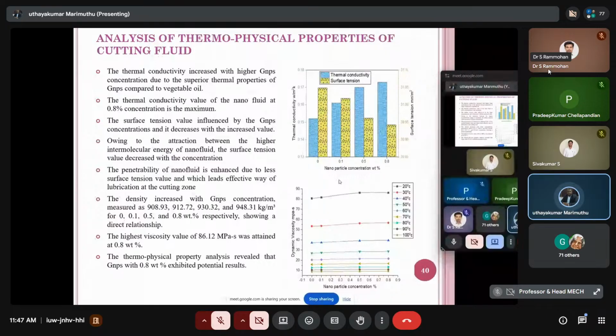The penetratability of nanofluid is enhanced due to the lower surface tension value, which leads to effective lubrication in the cutting zone. The density increased with the GNPs concentration, and the highest viscosity value is 86.12. The thermophysical property analysis revealed that GNPs at 0.8% weight exhibited the best results among all. Right, so that is the conclusion we made by using this study.